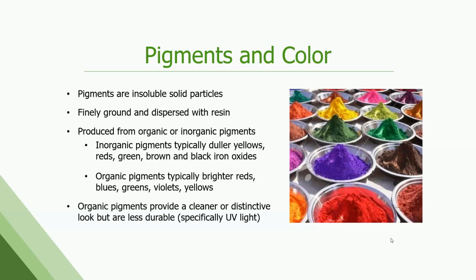Then you have your organic pigments. These are the bright primary colors, bright greens, bright reds, bright blues. They look great, but they're not very durable. I think we've probably all seen older red cars that have faded, or bright colors that have faded on signage, or somewhere in our world. They just don't hold up very well to UV light. So the paint companies spend a lot of time making sure that these pigment ratios are good so that we can achieve the color we want, but are also going to perform long term because they're going to get a lot of constant sunlight. You may need a clear coat if you use a lot of organic pigment to help protect it more out in the field as well. And that's also factory applied.